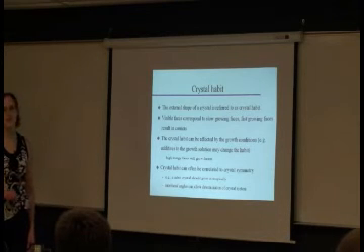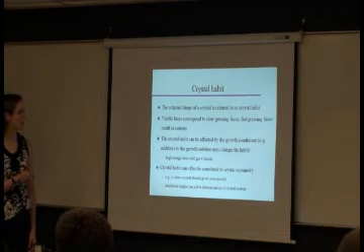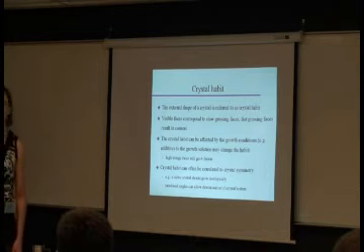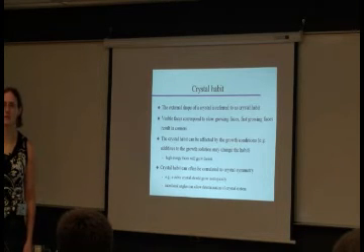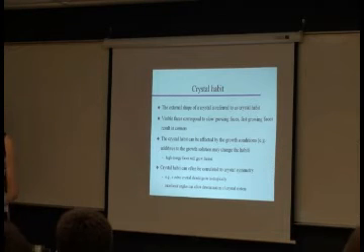Now, what should you keep in mind? You will have visible faces and you will have corners. Now, the visible faces are actually not the fast-growing faces, which is something that is very easy to think if you don't really pay enough attention to what you're talking about. A face that stays a face is not growing quickly. If it was growing quickly, you would have material depositing and you would form a corner. So the fastest growing faces will not be visible in your final product.